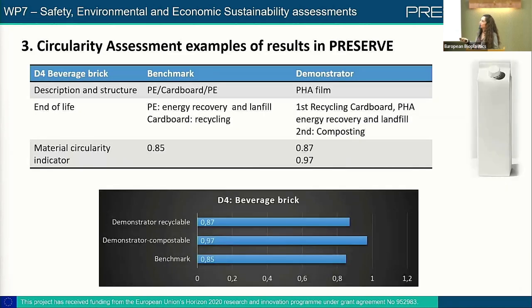And also, I have included here another structure. The demonstrator is not correct, so it's PHA film, paper, and PHA film. But we see, in this case, the improvement is not so high, because in the benchmark we also have cardboard. So this also has a high circularity in the indicator. For instance, the PE is energy recovery and landfill for the end of life, and the cardboard is recycled. So we have an indicator of 0.85, which is also high for the benchmark, really.